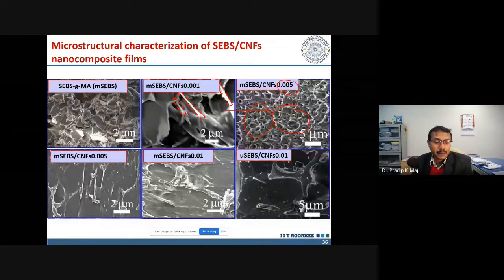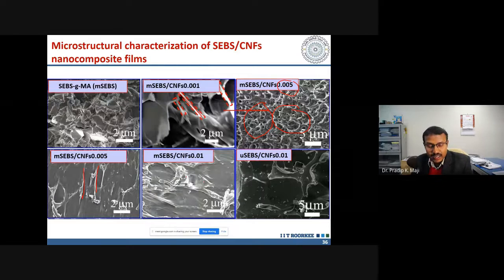And yes, after stretching with 0.001 and 0.005% addition of the CNF, fiber formation has happened, showing alignment of the cellulose fiber, and that's why it gives mechanical property improvement. Where, as there is increment of the cellulose fiber content, agglomeration happens and it breaks the cellulose fiber.